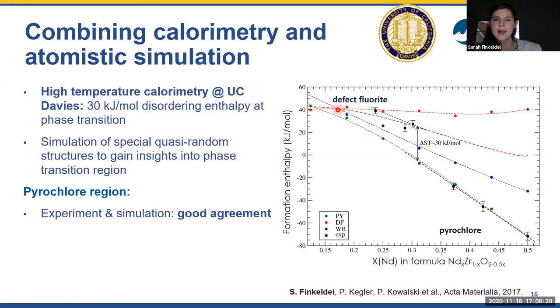So this was not when we found or realized this underlying higher ordering, but this was a second proof for it, where we say that the formation enthalpy of these disordered defect fluorites cannot be described with a pure defect fluorite structure or a pure pyrochlore structure. They can only be described if we have a combination of this ordered and disordered structure.